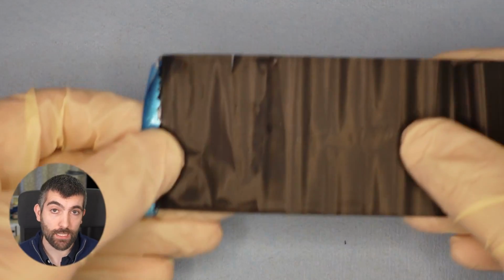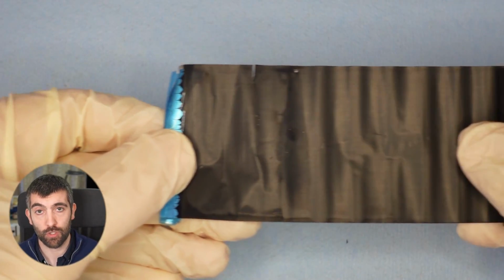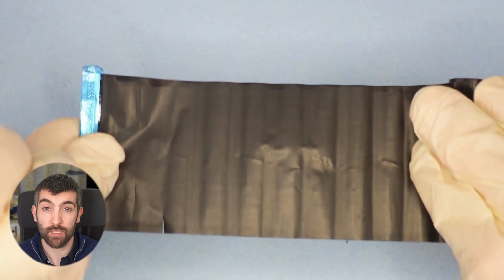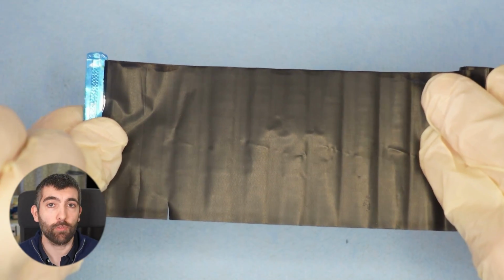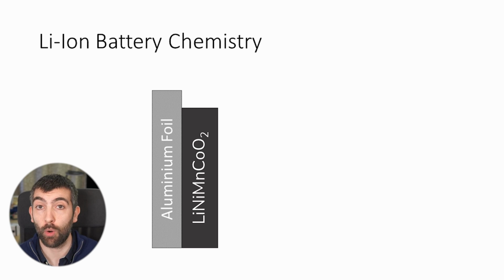Now that we've cut that battery apart, let's see if we can make sense of what we found inside it. Inside the battery were 2 sheets, an aluminium foil sheet and a copper foil sheet. Both sheets were coated with a dark material. The aluminium foil is actually coated with a mixture of lithium, manganese, nickel and cobalt oxides. All of those oxides are ground up, mixed together with liquid to make a slurry or a paste, applied to the aluminium foil and then rolled and dried to produce layers of that material.